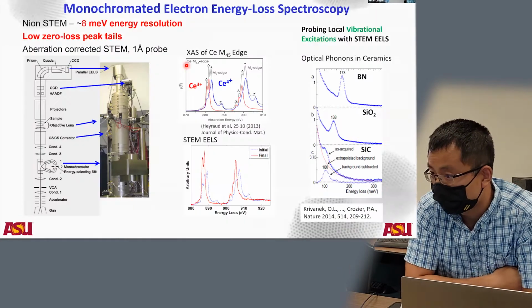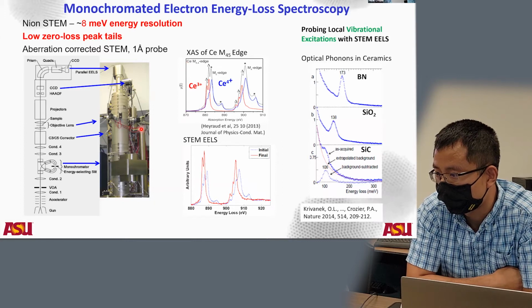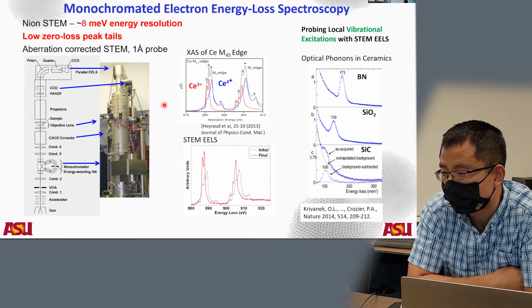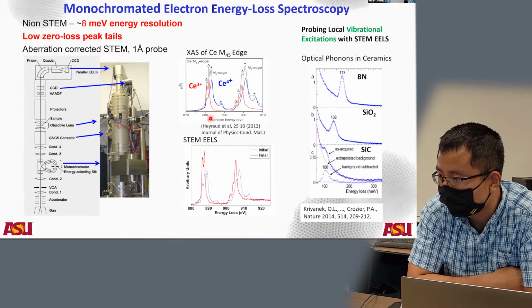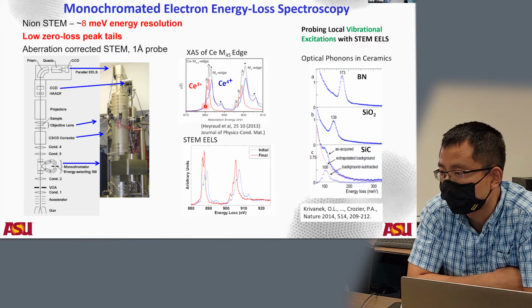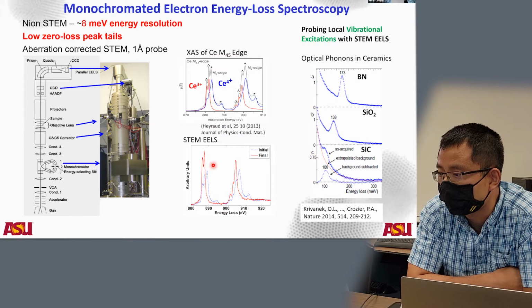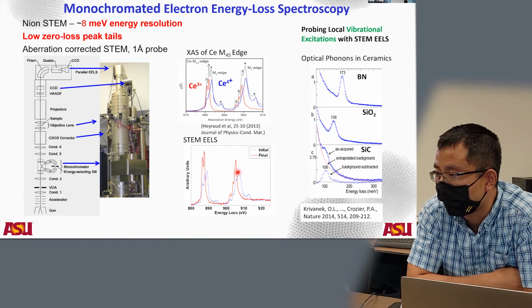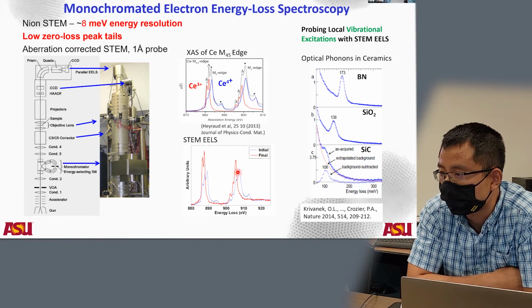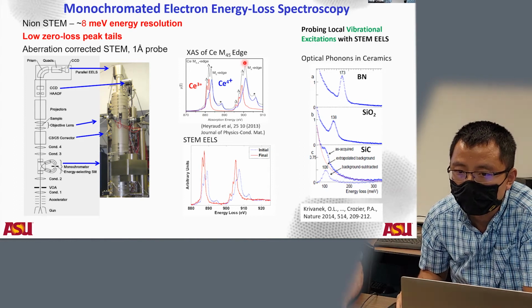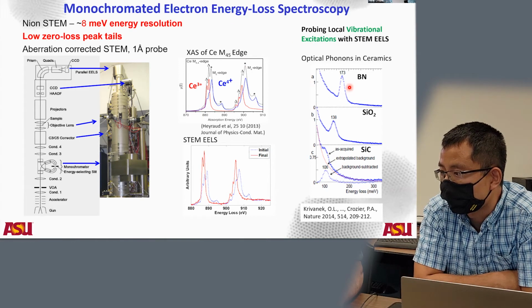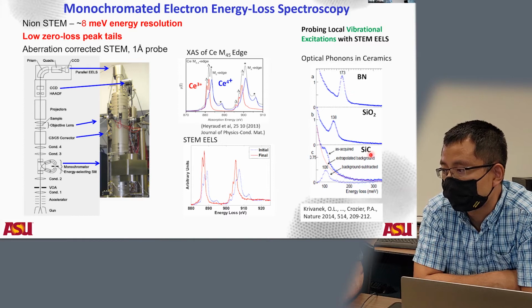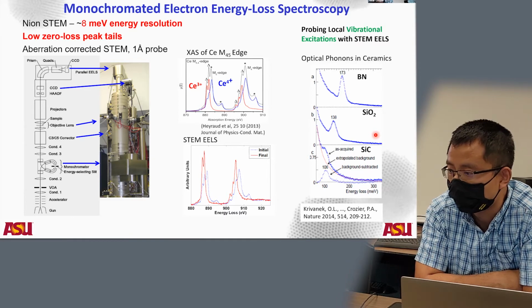With this particular microscope, we can do many different things. For example, with the core loss, for cerium, we can achieve decent energy resolution, comparable to X-ray absorption, to resolve the valence state of cerium atoms. And also with the low loss capability, we can measure the different phonon signals in different materials such as boron nitride, silicon oxide, and silicon carbide.